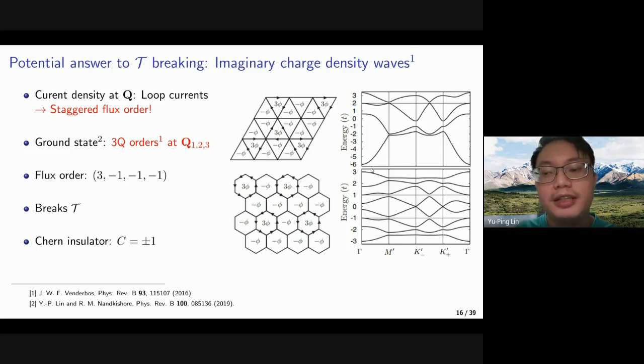And if we look at the band structure in the reduced Brillouin zone with half momentum scale, we find that for the triangular lattice, the Fermi level lies here, and we see that it is fully gapped. It is similar for the honeycomb lattice, where at the Fermi level in the particle and Hove branches, the bands are fully gapped. And it means that the band structure calculation shows that we are having a Chern insulator with a finite Chern number.